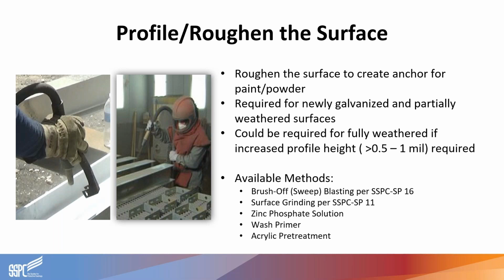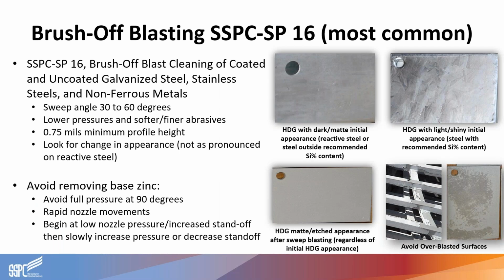But if you leave the roughening requirements unspecified and left fully up to the contractor, there may be instances with an insufficiently roughened surface for the coating you're trying to apply over galvanizing. The most commonly specified method for preparing galvanized steel for paint or powder coating is that brush-off blasting standard that I mentioned earlier, SP16. So this applies not only to galvanizing, but is also applied to stainless and other non-ferrous metals like aluminum.